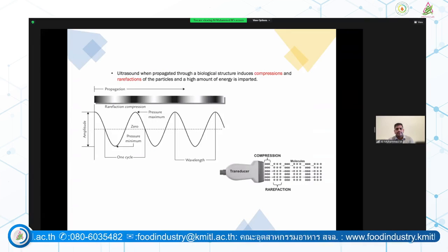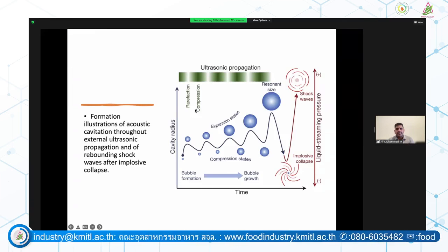In food science, we generally apply ultrasound technology in liquid systems, where the ultrasound propagates as longitudinal waves, and these waves create compression and rarefaction in the liquid medium. These regions create vacuum, cavities in the liquid medium, and these cavities create small air bubbles, which grow with time and become larger. Once they grow to a sufficient size, they collapse with intensive force. This intensive force creates shock waves in the liquid medium.